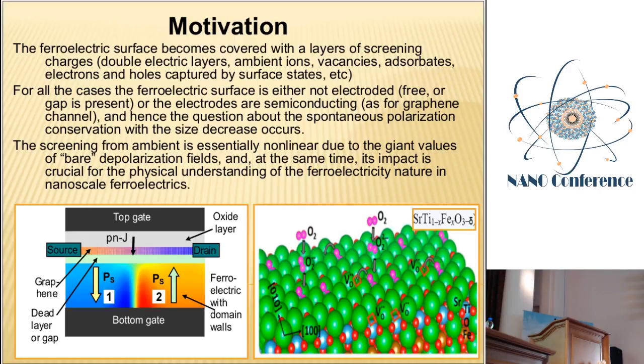And in this case, when the surface of the ferroelectric is electrically open or partially open or covered with imperfect screening, it can be an imperfect electrode, it can be ambient gas or solution, the critical thickness is typically much higher than the limit of 10 nanometers. It can be, for instance, several hundred nanometers or even microns. And this is a problem for device miniaturization. So, we should work on the question of how to choose appropriate screening conditions which allow us to decrease the critical size and to conserve the ferroelectric state as long as possible, as well as to control the peculiarities of the domain formation. One possible escape is to choose the so-called ionic arrangement, because ions can also effectively screen the bound charge.